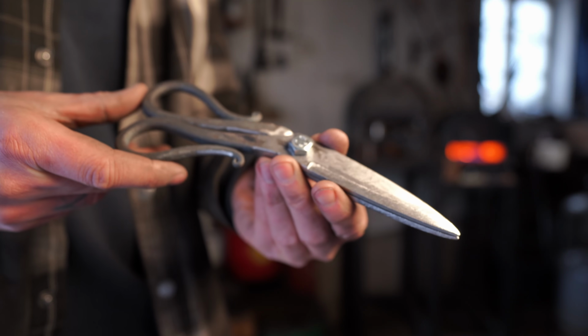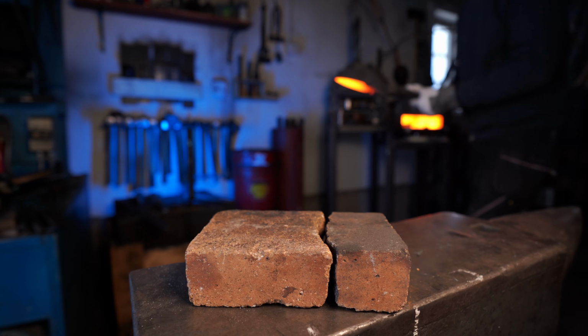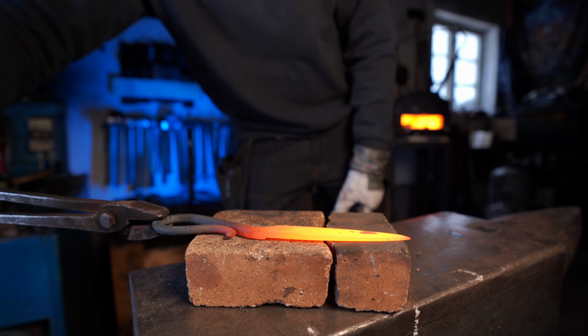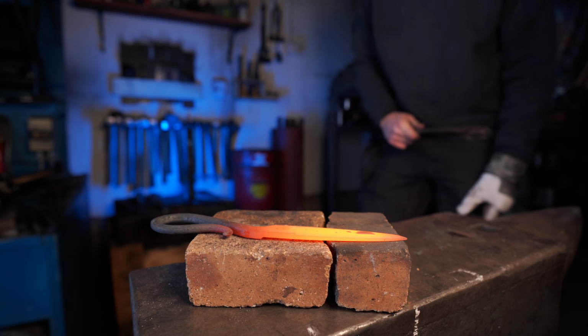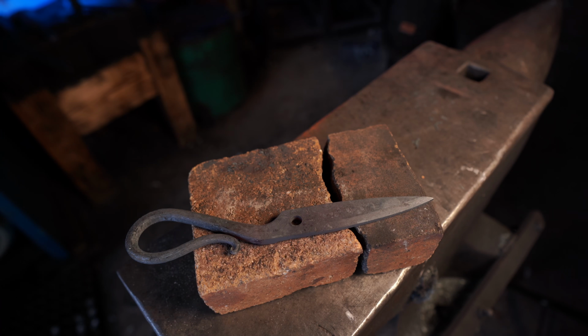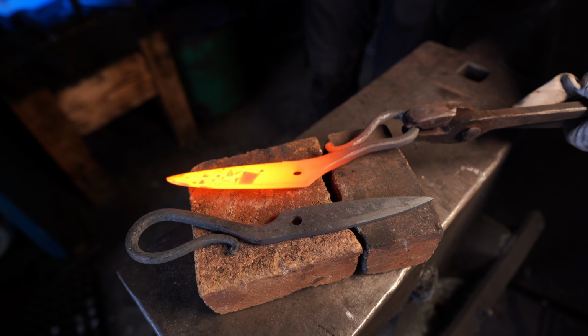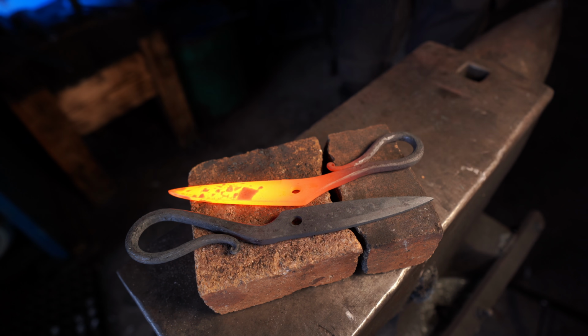It's time for heat treatment, and the first step is to normalize the blades. I do that by simply heating them up and letting them cool down slowly at room temperature. That normalizes the grain structure and makes them ready for hardening.